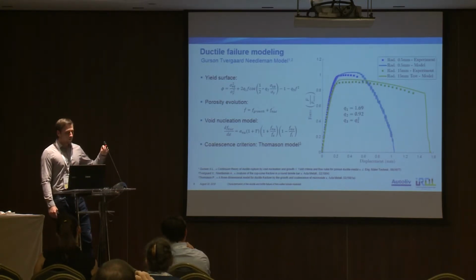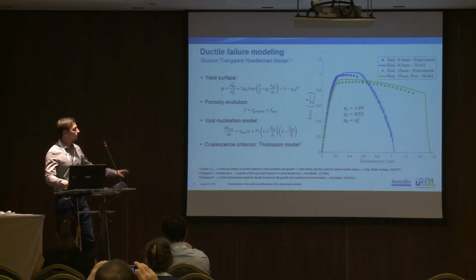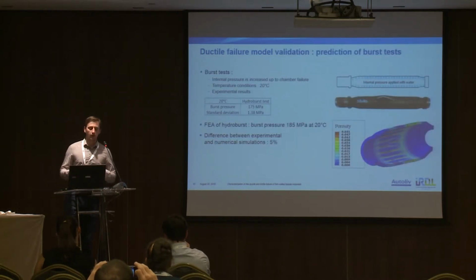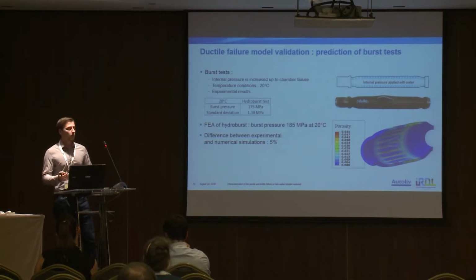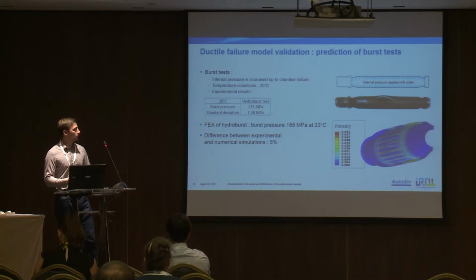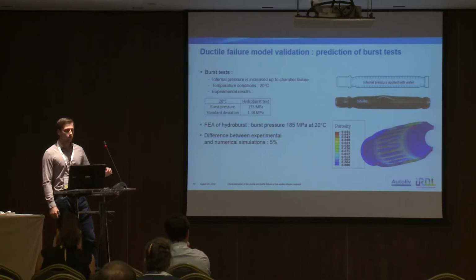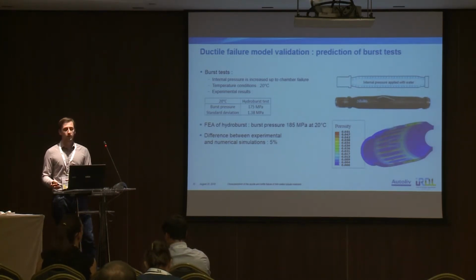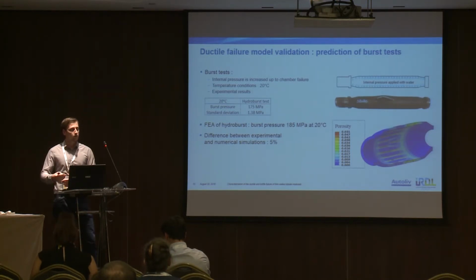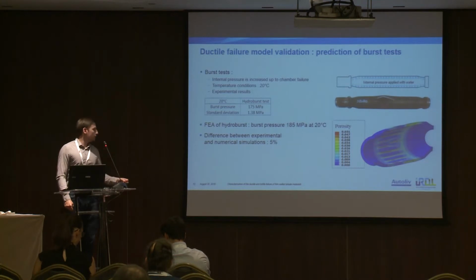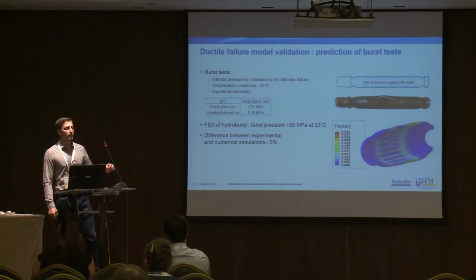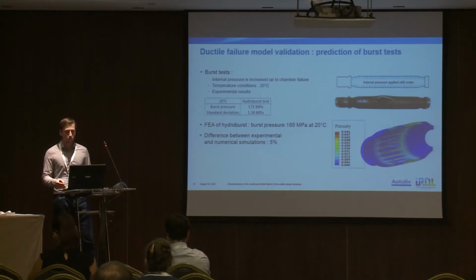So we were satisfied with this fitting, and then we tried to validate this model. To validate this model, as well in an industrial context, we have to use a different test with no link with the previous tests. So, here we are using a burst test. This is a really simple test because we apply an internal pressure into the chamber, and we increase this pressure up to rupture. When rupture occurs, we measure the pressure level, and then we compare this level with the level obtained with the simulations. Finally, results show that we have less than 5% of difference between experimental and numerical simulation. So, with this result, we can say ductile failure identification is finished.